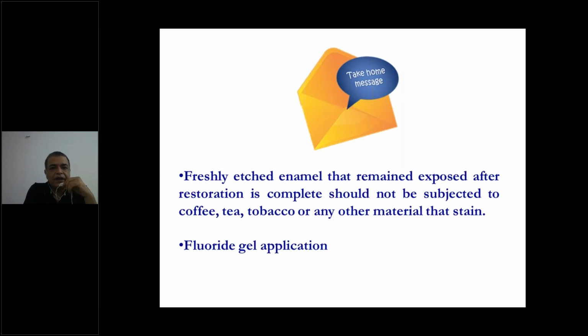This is another area of concern. Many times when we etch a tooth, especially in anteriors, we etch areas which may not be part of the restoration. That area has become demineralized, and when it is subjected to coffee, tea, or tobacco, it will stain. So you will have a restoration which is well polished, but the area around it may be stained. So if you have done that, I would recommend doing a fluoride gel application in that area before you send the patient home.